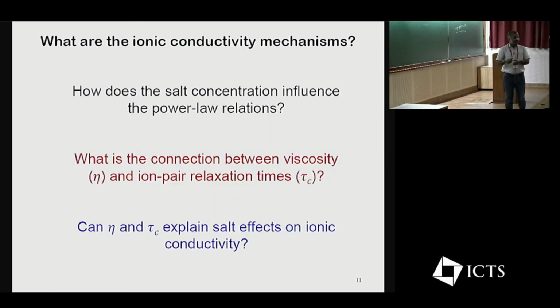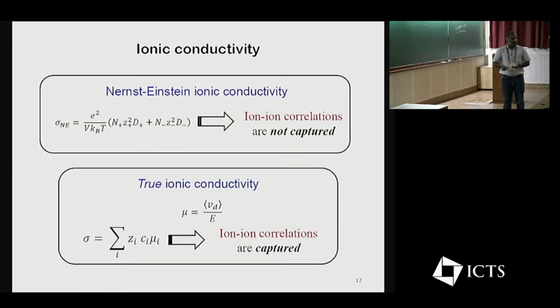all-atom MD simulation wherein the intra- and intermolecular interactions were modeled through a classical force field. Then we performed MD simulation within the framework of linear response theory, using either an equilibrium approach or a non-equilibrium approach to calculate all these quantities that I just mentioned.